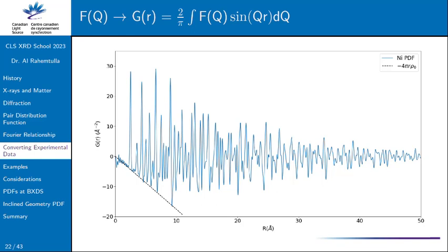So this is somewhat similar to an EXAFS technique, but it's using diffraction instead of X-ray absorption. The difference here is that with EXAFS, you're looking at the shifts that show fingerprints for bond lengths. This is a direct Fourier transform of the signal that gives you that R distance. Just to verify, the X-axis will give you distribution distances around one particular atom type.